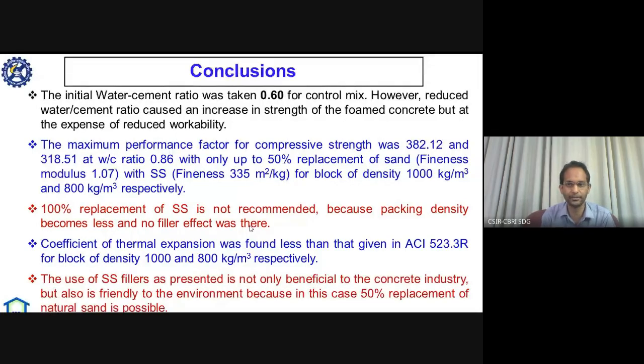Now what I have mentioned, this fineness modulus, normally if you see the table given in IS 383, there are 4 kinds of zones. But we have taken the river sand, that is Solani river sand, which has fineness of 1.07, because as per British Cement Association, the sand we want to add to develop lightweight concrete should have fineness less than 1.25. Therefore, we have chosen very fine river sand, and the stone slurry, of course, has fineness 335 meters square per kg, which is quite more than that of cement. And as you know, the cement fineness is typically about 260 to 270, with minimum 225 meters square per kg as per IS 8112 code.